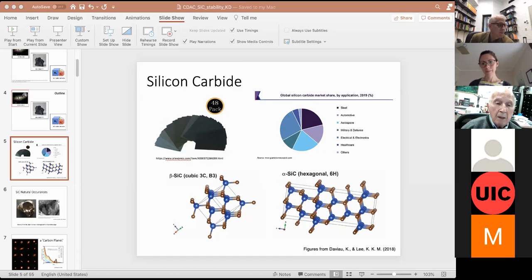More questions? It's Roald. I have a comment also. The oxygen and silicon carbide work is very interesting. If kinetics is important, I would think also about another possible product, which is silicon monoxide. That's not what you usually think of because silicon dioxide is so stable. But just to make the point in another context, just because CO2 is so stable does not mean that carbon monoxide does not exist and is kinetically stable. So we have predicted some structures for silicon monoxide under high pressure. None of them ever get near stability of silicon dioxide, but they are interesting in their shapes.